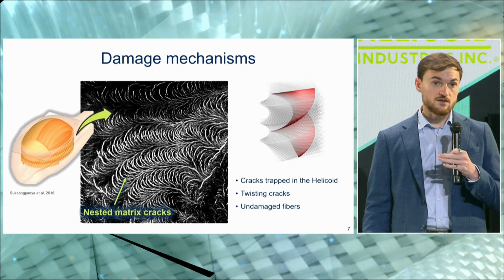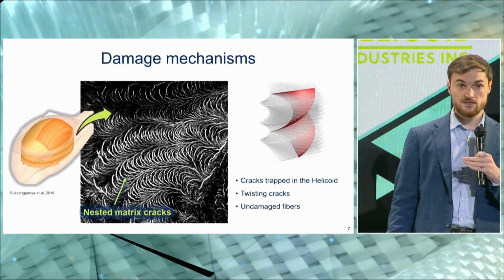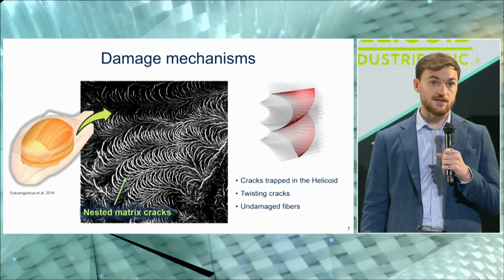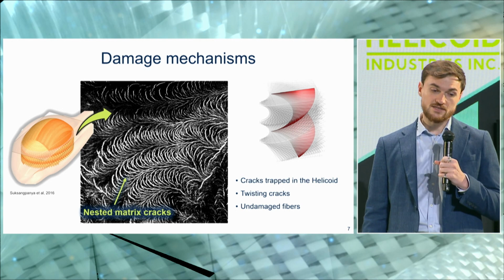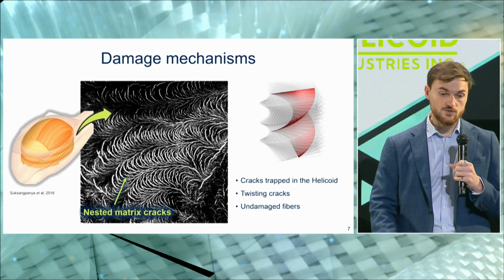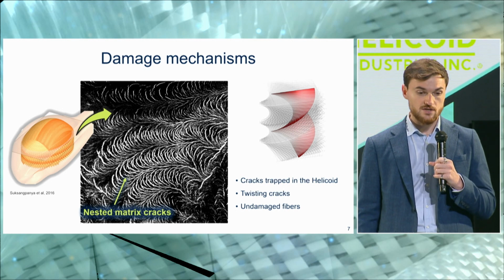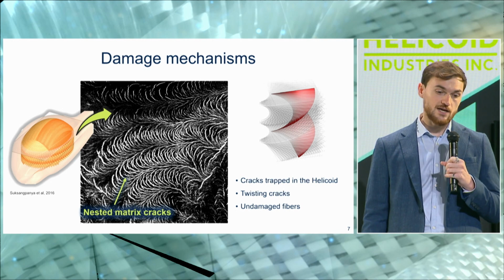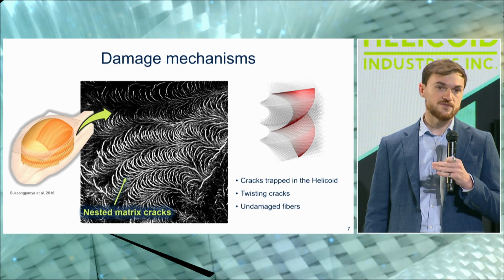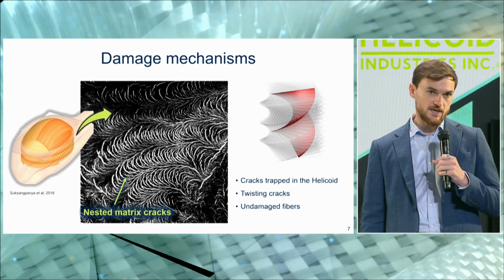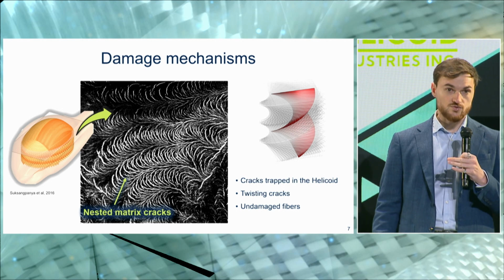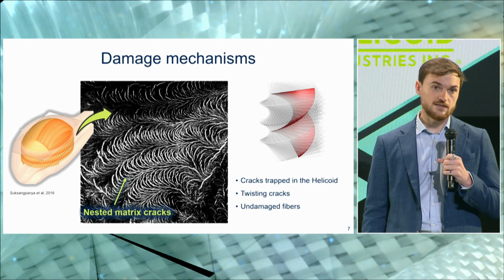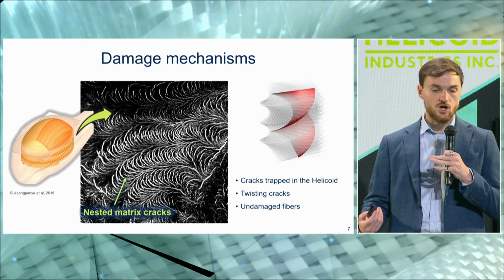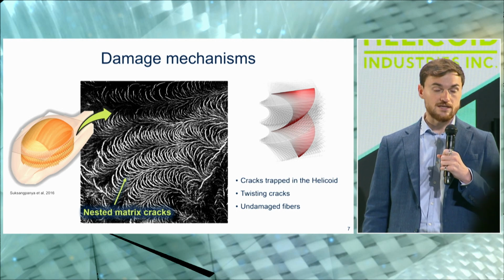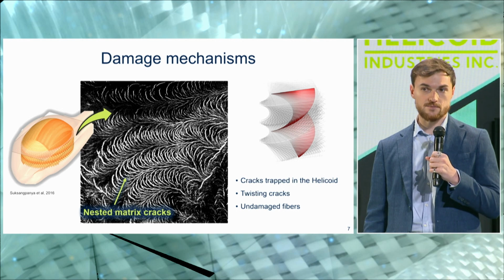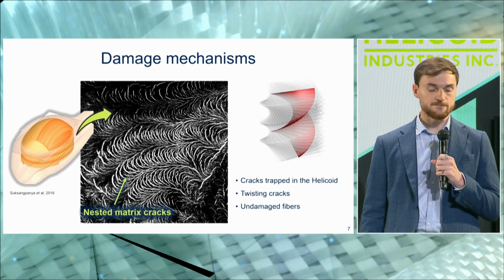The benefit of these are, first of all, we reduce interlaminar stresses. Therefore, we allow to delay the delamination onset in the composite. But more importantly, when damage initiates, you get this type of failure in the structure, where you can see a cross-section of the actual club, and in white you see a lot of matrix failure. So the energy gets dissipated through matrix cracks, diffused through matrix failure, and you leave fibers undamaged. You create these highly complex fracture patterns in your structure that allows you to dissipate energy, but at the same time to preserve a very high structural integrity.